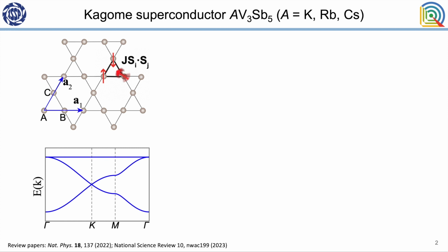A Kagome lattice is formed by corner shared triangles. Such a spatial lattice provides an ideal platform to study the interplay between the correlation, band topology, and the lattice geometry. Because there are Dirac band and a flat band and Van Hove singularities in its electronic band structure, shown in this figure. So interplay of these Van Hove singularities will introduce the nesting of Fermi surface and stimulates the electrons to form a charge density wave and superconductivity in low temperatures.